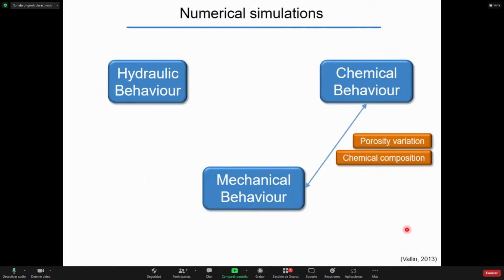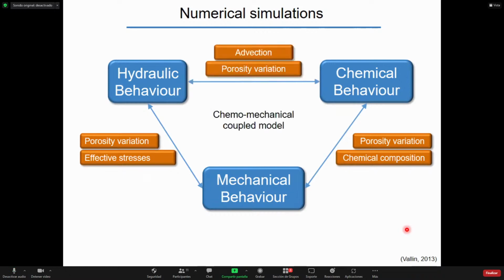Carbonation induces chemical variations and porosity changes as well. This modifies the mechanical behavior of the specimen, and porosity changes also modify the diffusion and advection phenomena. By modifying the diffusion and advection, the chemical reactions are also limited over time. This is the chemo-mechanical coupled model that we use, and that was implemented in a finite element method in the code.